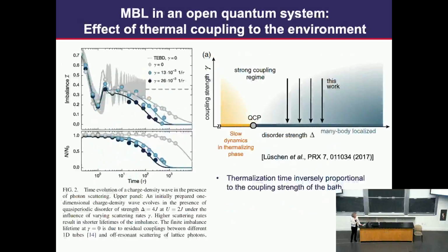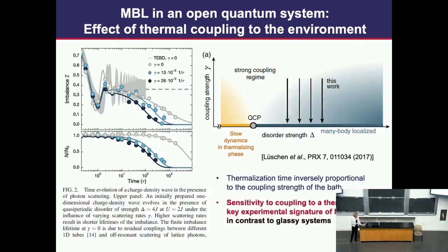In the experiment, these people also actually tried to increase the coupling to the environment, and then you'd expect that the MBL will break down faster, the system will thermalize faster, and this is indeed what they observed. So it is really this very strong sensitivity of this MBL system to coupling to a thermal bath that is a key experimental signature of MBL, in contrast to glassy systems that are robust to that.